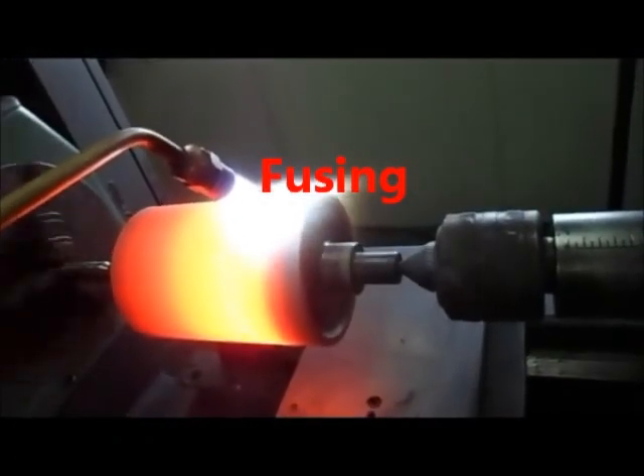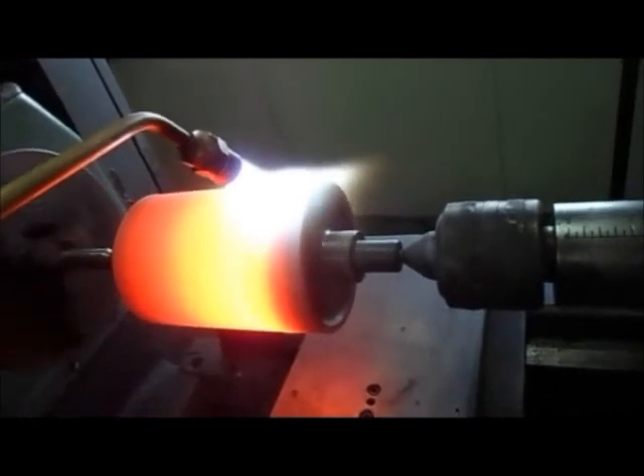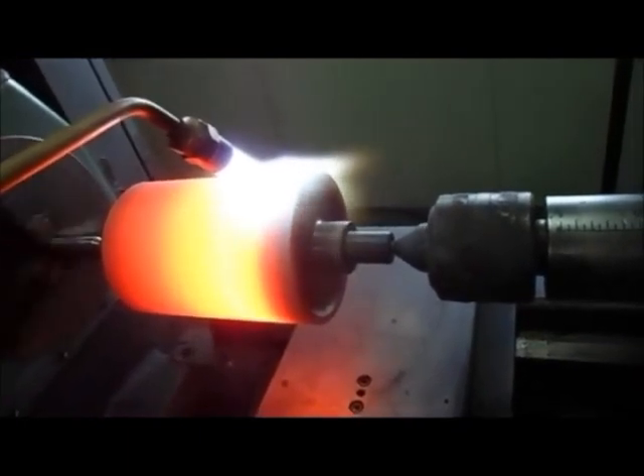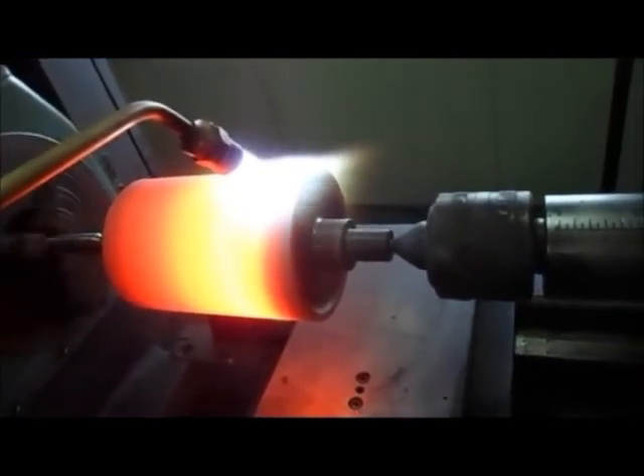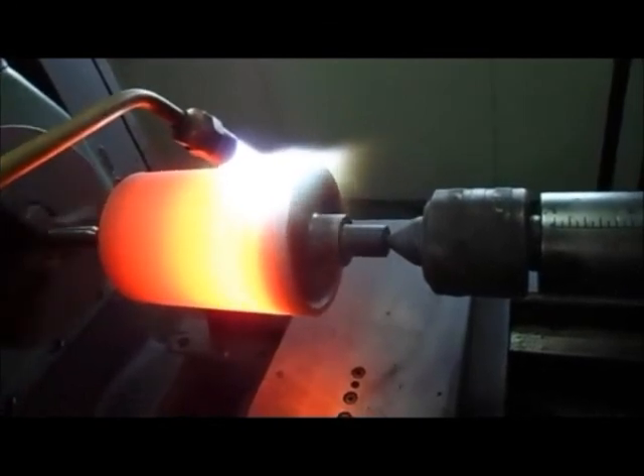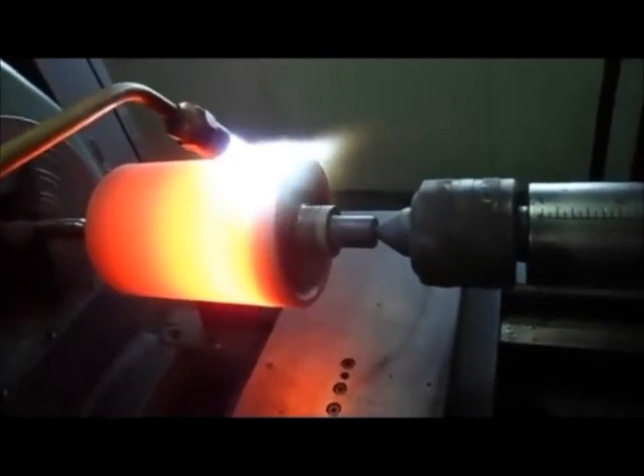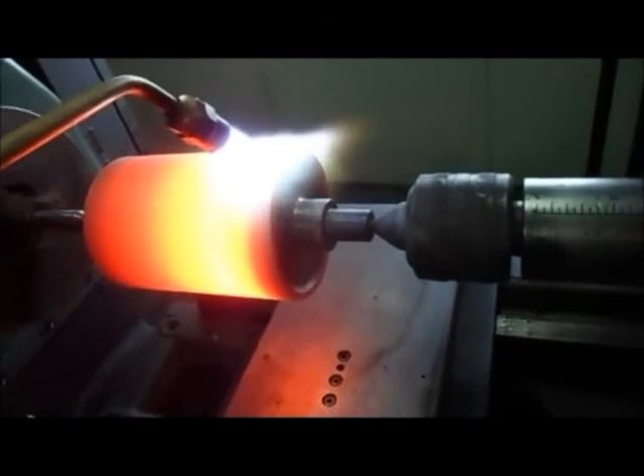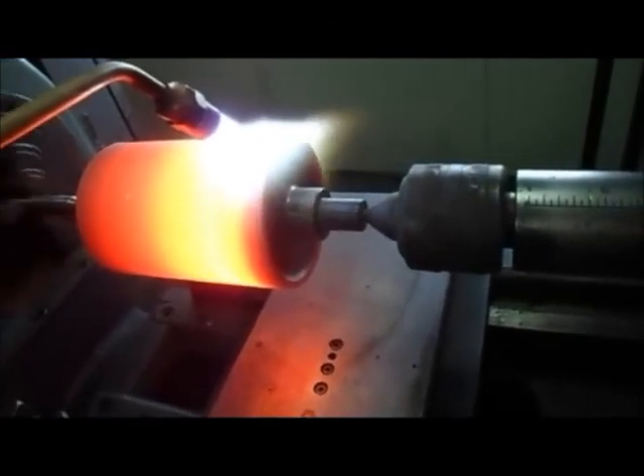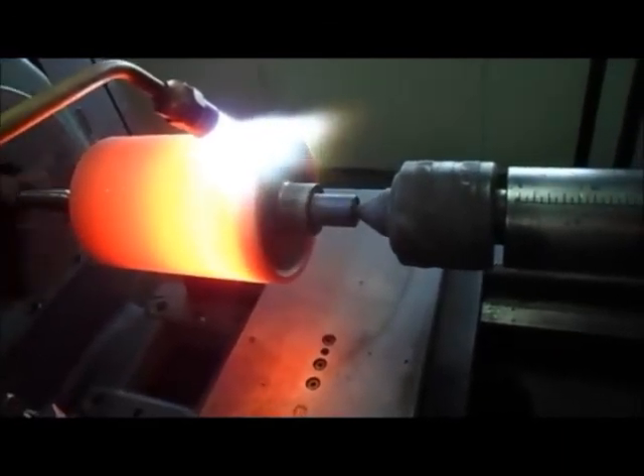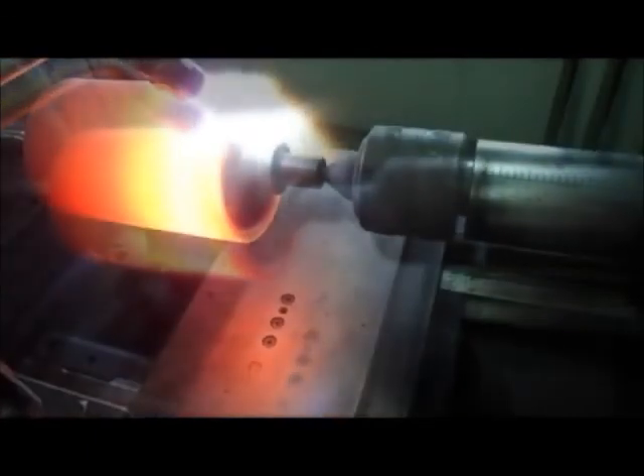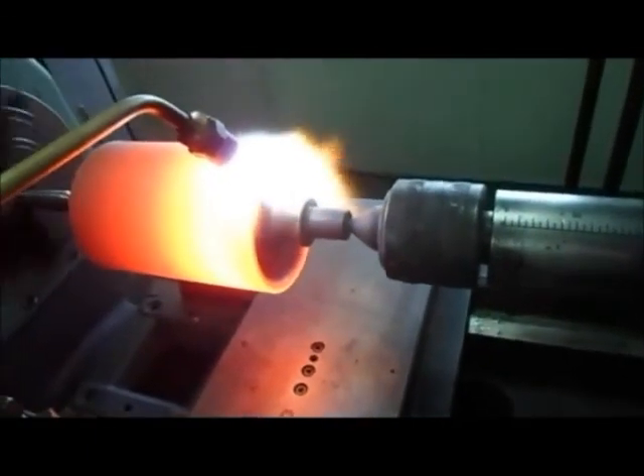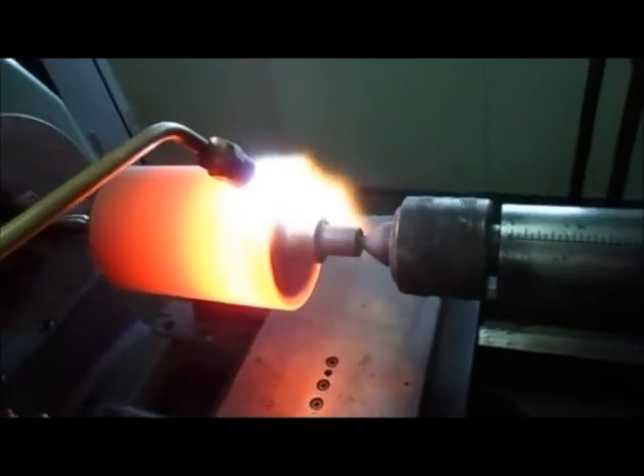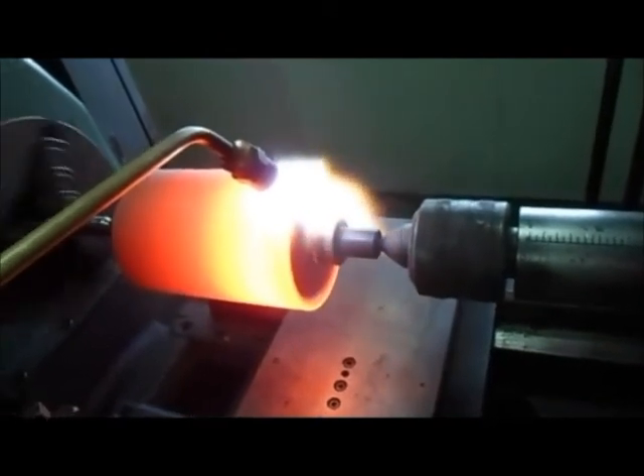Fusing. Thermal spray coating makes a lot of porosity in the coating layer with less bond strength essentially. The sequence process to improve sprayed coating layer is fusing. The fusing process remelts the coating layer by heating and results in less porosity with higher bond strength. This thermal process also has similar critical difficulties to hard facing.